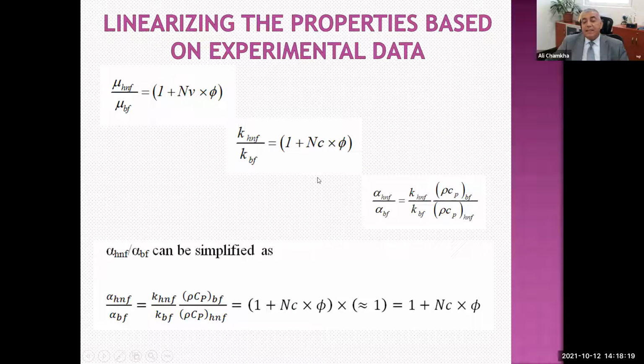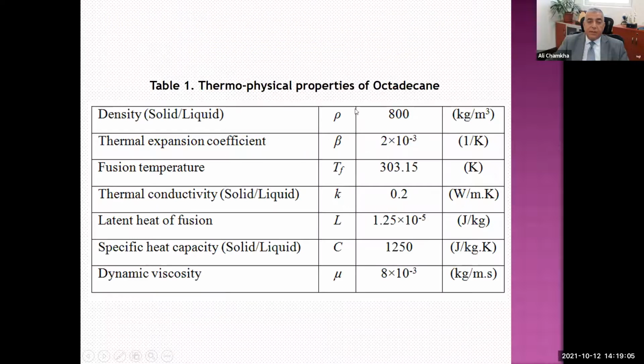Now here what we did, we had some experimental data, and we have linearized them to look like a linear curve like this in terms of a coefficient. We called it the viscosity coefficient, in terms of volume fraction. And these are real data that we have modified. I will show you in a minute. We have also linearized the thermal conductivity data, and this is the thermal conductivity constant. So these are the two models being used, and then the ratio of the thermal diffusivity for the hybrid nanofluid. NC is the coefficient or parameter for enhancement of thermal conductivity.